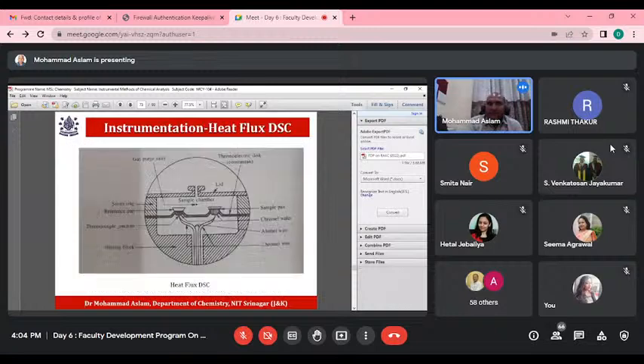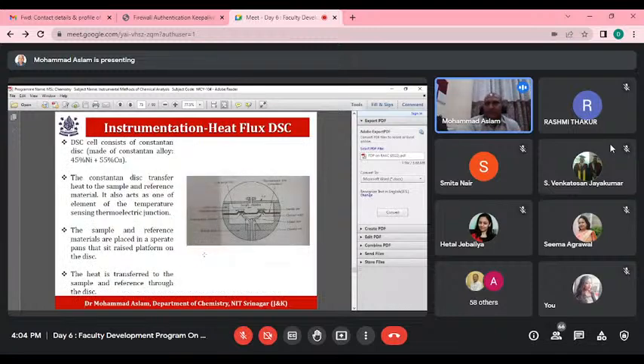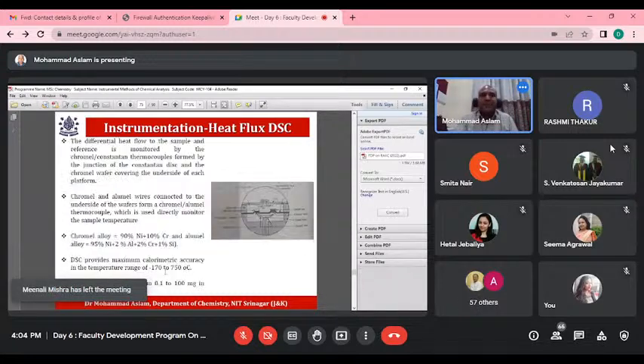So here, I think this is a very important slide, because this cell basically consists of this Constantan disc, an alloy of nickel and copper, and this Constantan disc provides the heat, transfers the heat to the sample and the reference material. The sample and reference material are placed in separate pans, which sit on the Constantan